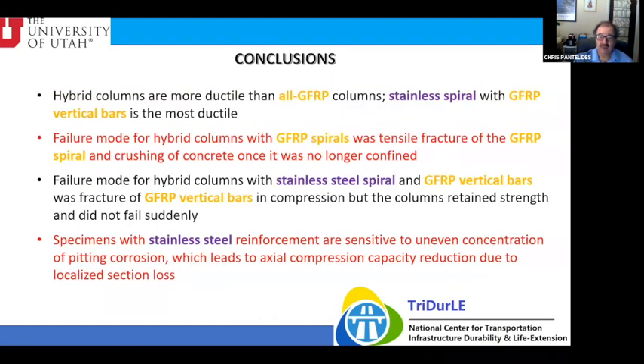So the hybrid columns are more ductile than the all GFRP columns. We saw that. The stainless spiral with the fiberglass vertical bars was the most ductile. The failure mode for hybrid columns with GFRP spirals was tensile fracture of the fiberglass spiral and crushing of the concrete once it was no longer confined.